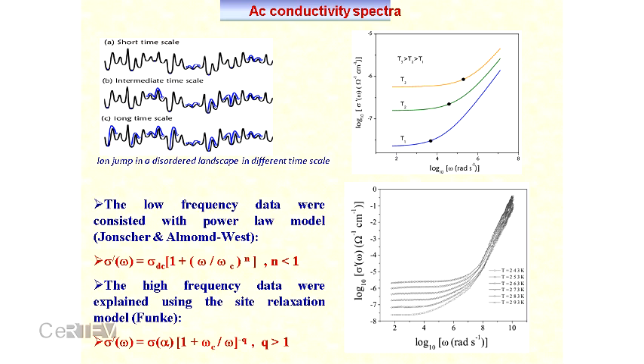One is the Jonscher law, modified by Almond and West, in the low frequency, dispersive region. Here it is the DC conductivity as a function of omega by omega to the power, where this frequency is the crossover frequency, where the DC to dispersive crossover starts, and the exponent is always less than 1. In the high frequency regime, it can be described by another power law, and in that power law the exponent is greater than 1. So we can at least assume that the mechanism of conduction, or AC relaxation, whatever you call it, is different in these two regions. I shall focus primarily on the low frequency region, which can be characterized by these equations, the so-called modified Jonscher law. So we have this at hand,